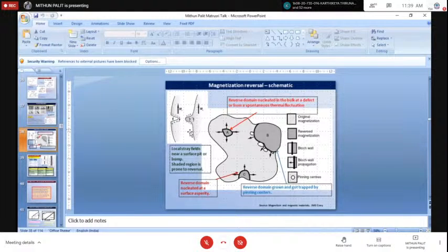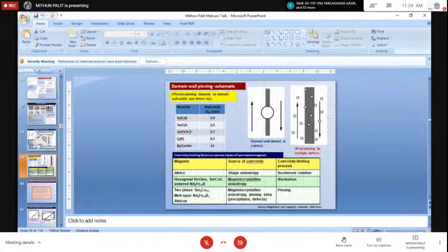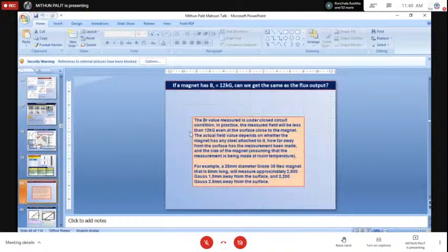So this way we can lose the property of the magnet. And I told you that in the case of pinning there will be different boundaries, and if those defects and boundaries present in the material are comparable in size to the magnetic domain boundary, then we can see this kind of pinning. So therefore, for this pinning as well as nucleation, we have talked about different phases, different grain boundaries, and so on, and there lies the role of processing the magnetic material for correct microstructure engineering.